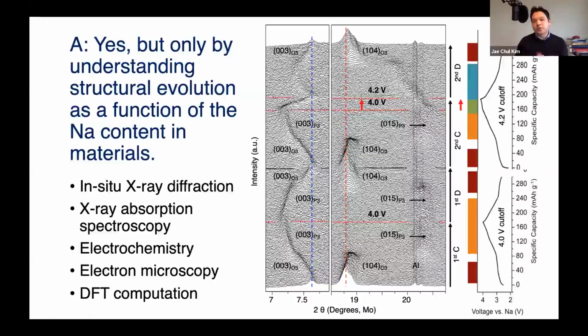As you know, X-ray diffraction gives you long-range information about the material structure, but we do want to know the local environment of the material, especially around the transition metal, because the transition metal is the center of the redox reaction, which is critical to store electrons. And that can be done by various techniques such as X-ray absorption spectroscopy, and of course, electron microscopy. And if thermodynamic understanding is required, then we can also do DFT computation along with the electrochemistry.